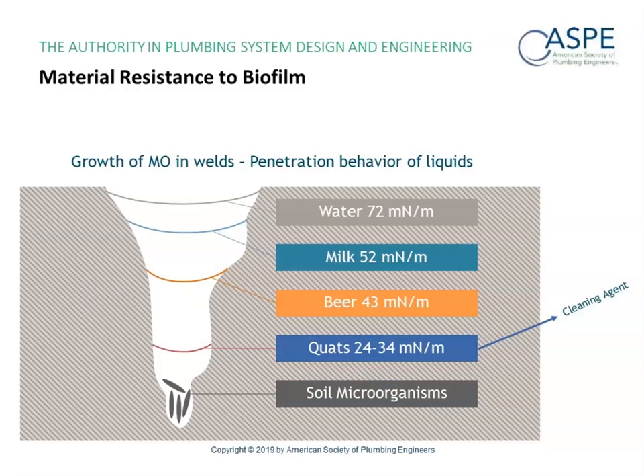Milk penetrates deeper than that at 52 millinewtons per meter. Beer, which I'm recommending as a cleansing agent, just not in this case, is penetrating at 43 millinewtons per meter. Quats, which is a cleaning agent, gets down to 24 to 34, which is not enough to penetrate deep enough to reach the soil microorganisms.